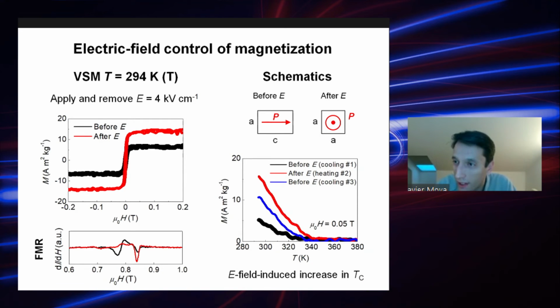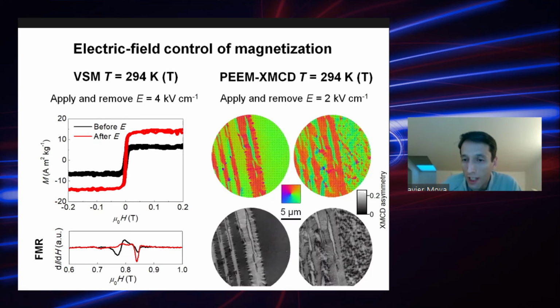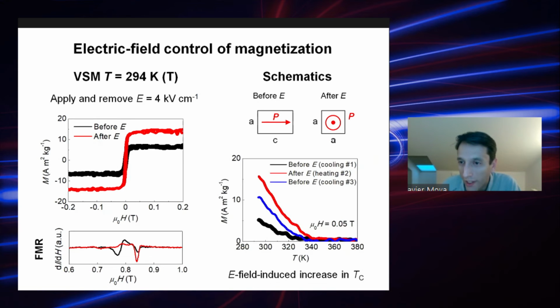This changes the exchange interaction between the manganese atoms and decreases the Curie point, and therefore also the magnetization. So what you can expect is that these regions here are regions where the polarization in the substrate is in plane, so the film is very strained and the Curie point is depressed, so the magnetization is small. And then when you apply an electric field, what you do is you switch these domains out of plane.